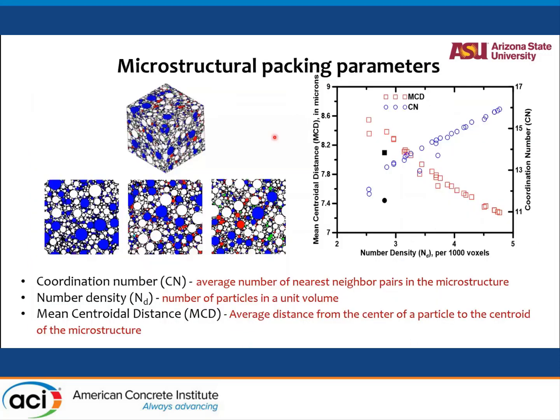And then we did particle packing, computational particle packing, assuming everything is spherical particles, not the ideal situation, but there is a lot of work that has shown that considering them to be spherical particles and packing them in a three-dimensional volume will give you reasonably sufficient results to make decisions as to what set of particles to choose. Doing the real shapes is very complicated, so we just do spherical shapes.